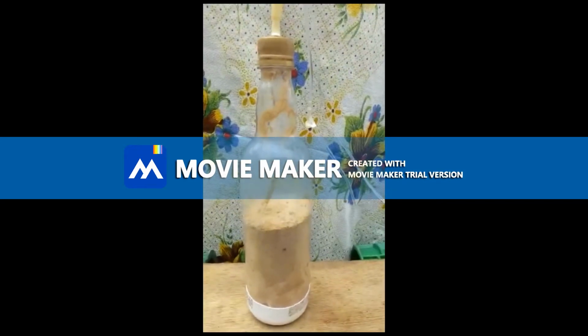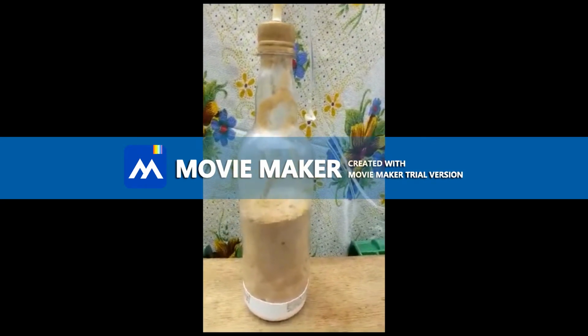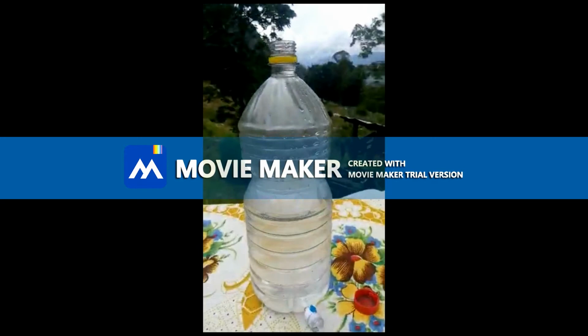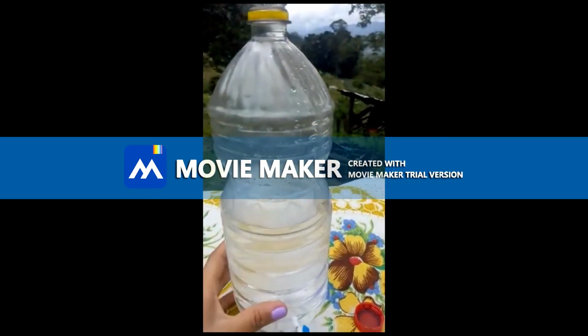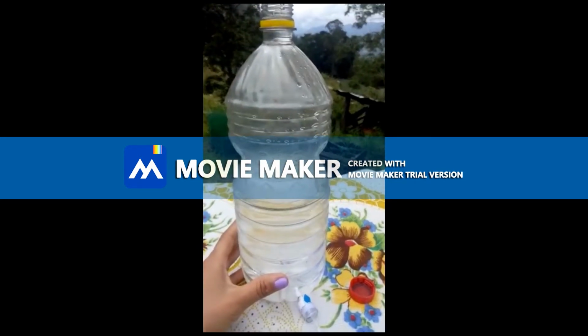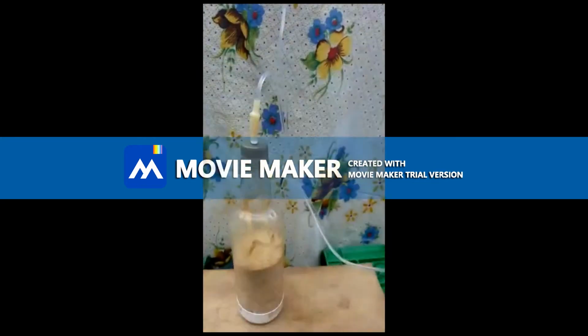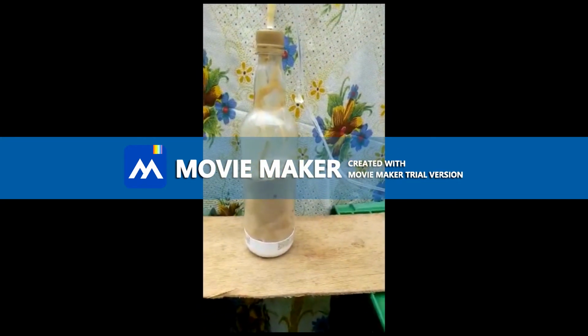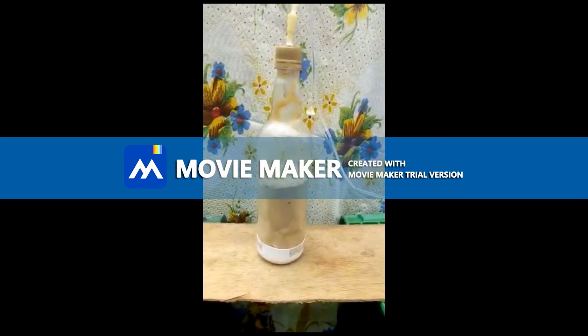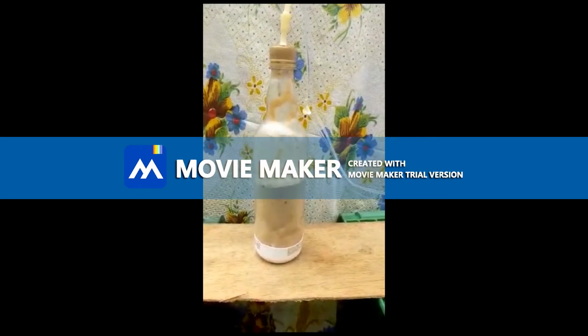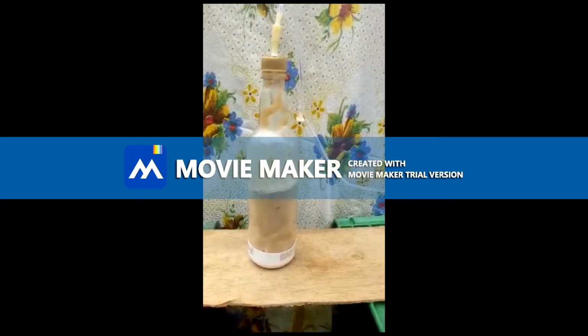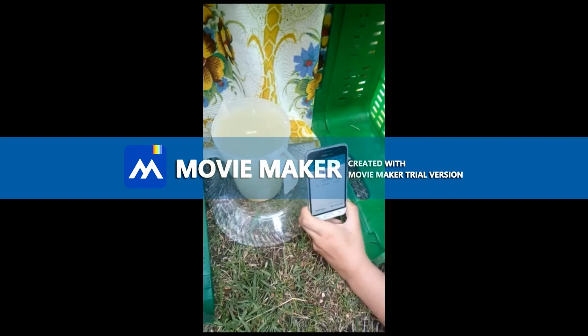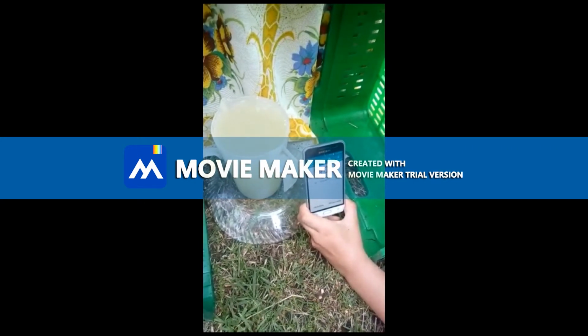The first step is to place the sand inside the bottle. Then, fill the reserve tank with a known volume, in this case 1 liter. Finally, the solid holder is filled with water. At this moment, start the chronometer and collect the water that passed through the solid particles. 1 liter passed in 54 minutes.